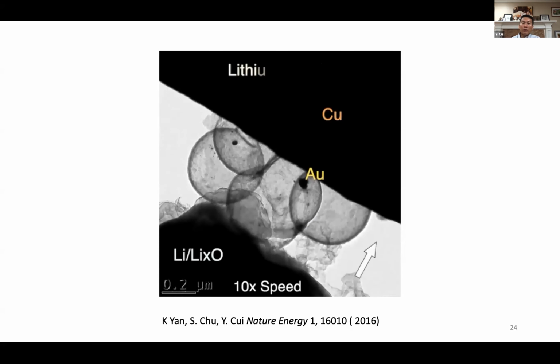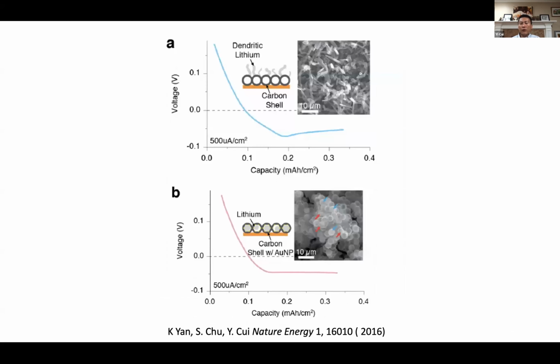This is really trying to show you the concept of this phase diagram, that lithium can dissolve gold. Using a seed at the bottom of this hollow carbon, with gold in there, we could deposit lithium up to a certain capacity, with only lithium going inside. The top case is hollow carbon without the seed, and you see filamentary lithium metal deposition outside, really proving the concept of spatially controlling where the lithium will go. So the bottom case allows you to cycle the battery during charging and discharging with much better stability.